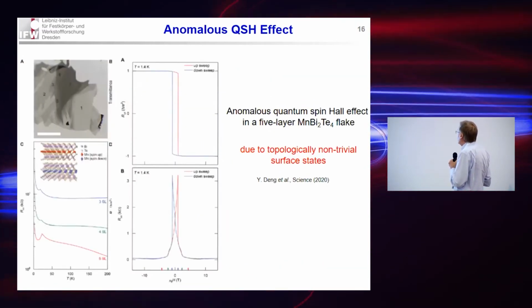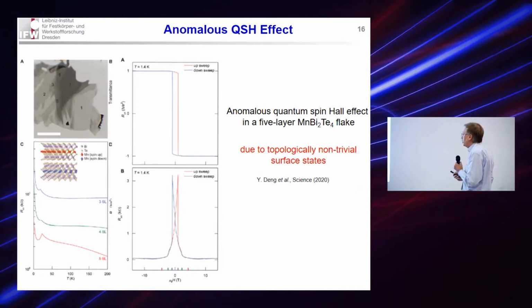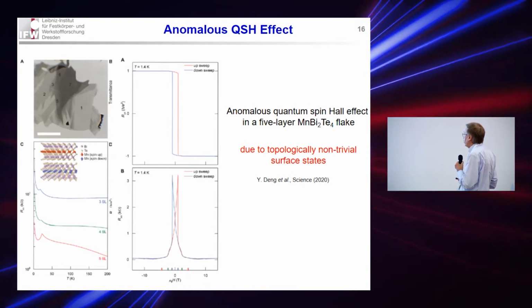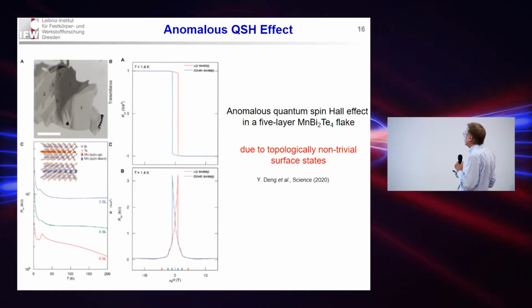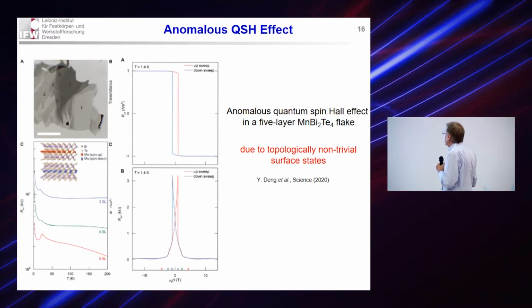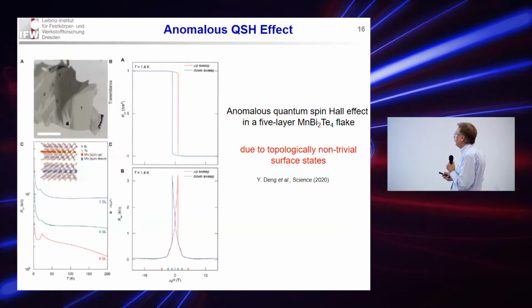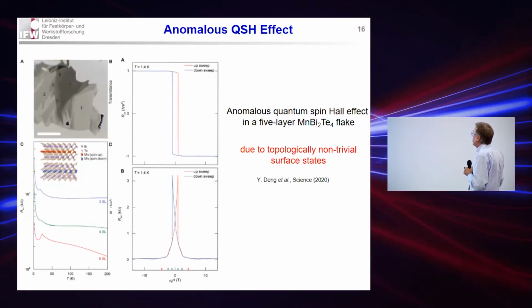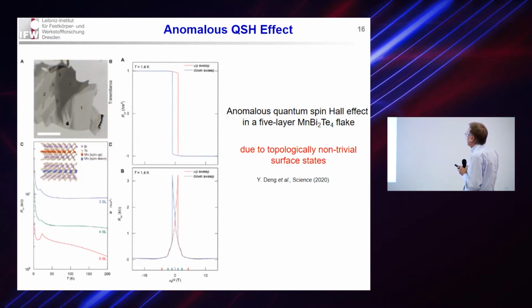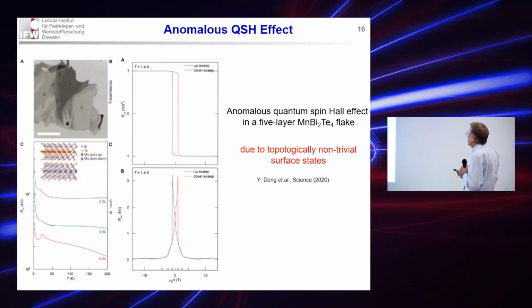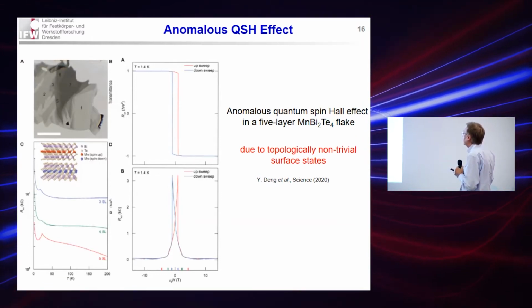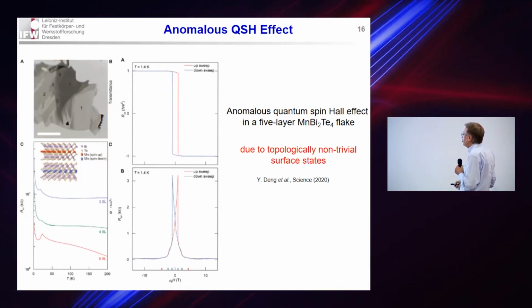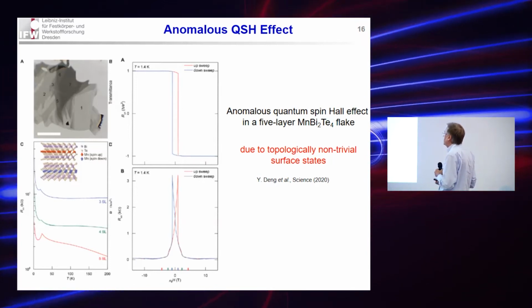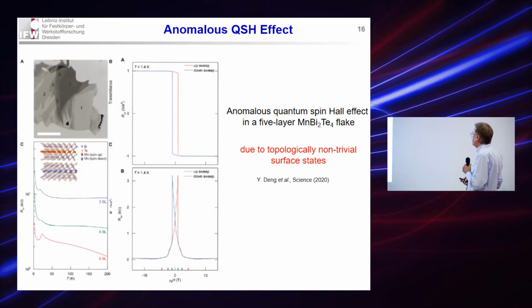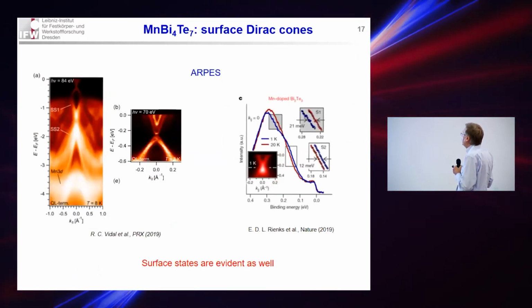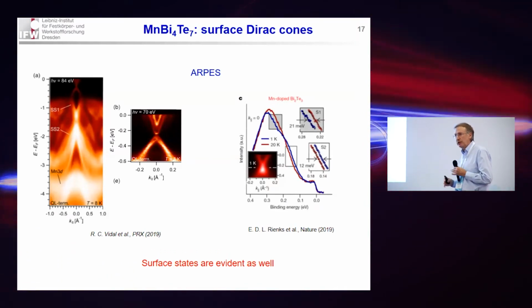So this material 124 is indeed a topological magnetic insulator, which was ultimately confirmed also by measurement of the anomalous quantum spin Hall effect by Y. Deng et al.. It was published quite recently. They measured it on a thin flake, a few-layer flake of the single crystal, and indeed observed these quantized jumps in the transverse Hall resistance and the divergence in the longitudinal resistance, proving that this is a magnetic topological insulator.